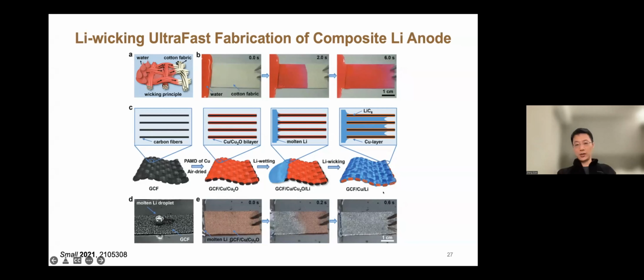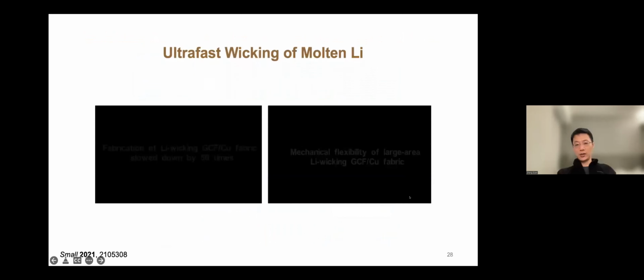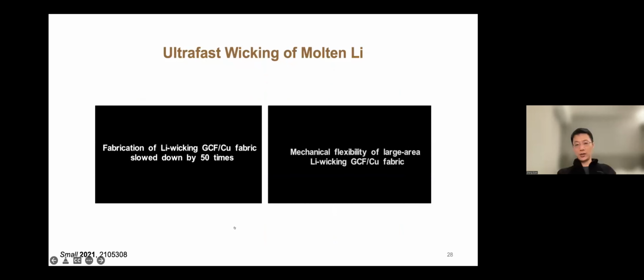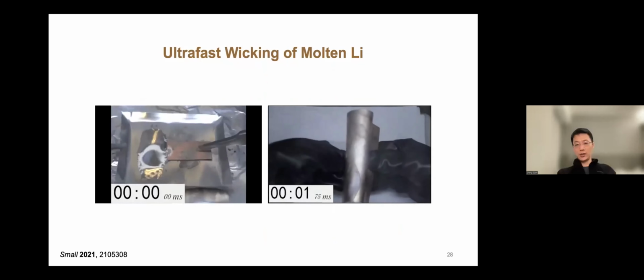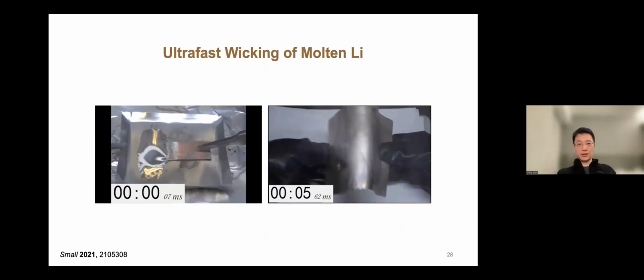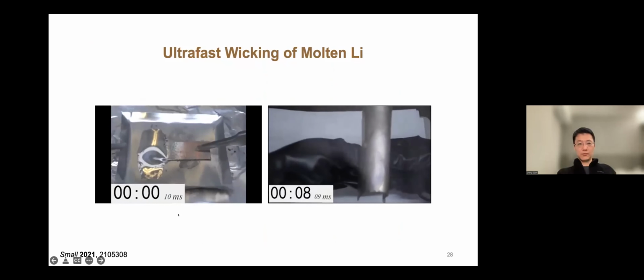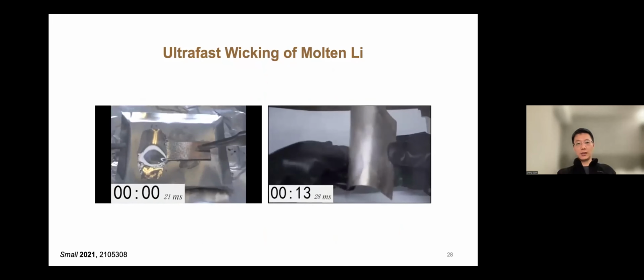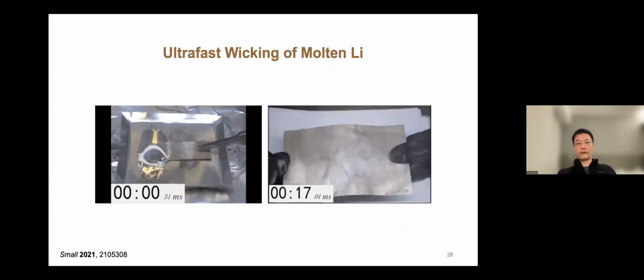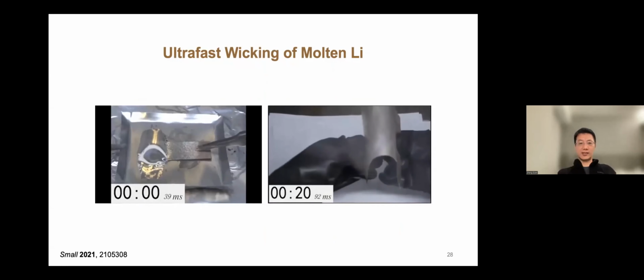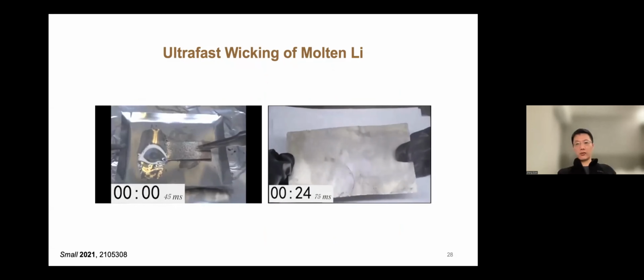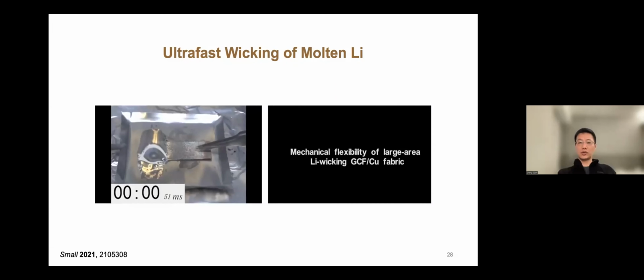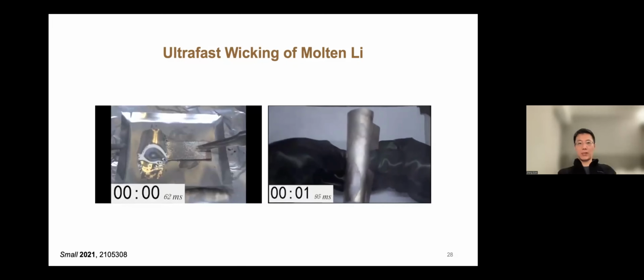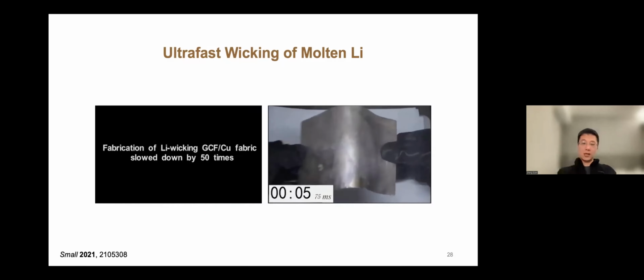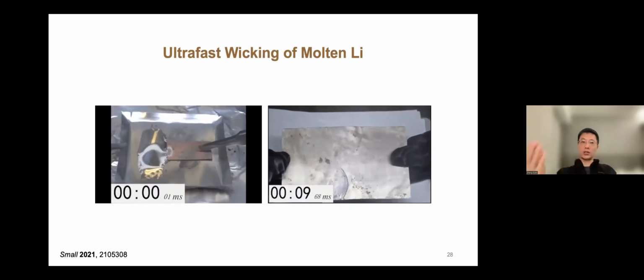You see this time is 0.6 second, that's 600 milliseconds. I show you two video clips. On the left-hand side is a video clip showing the wicking process slowed down by 50 times. The unit is milliseconds. Already at 20 milliseconds, half of the current collector has been fully wicked with lithium metal, and when you reach about 50 to 60 milliseconds, the entire sample, which is about 3 millimeters long, has been fully wicked. So we believe in the future we'll be able to use similar technology to make a very high speed of fabrication. This speed is already about 10 meters per minute, which is far over the battery coating speed. And once you get it, it's a big sample that shows how flexible it is.